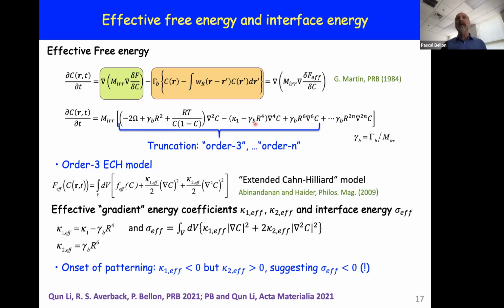But when we look at the second term here, there's something intriguing: when we increase gamma, we may also change the sign of this gradient energy coefficient. And since this is related to the interface energy, that suggests that pattern formation can possibly be envisioned as a mechanism by which irradiation changes the sign of the effective interface energy from positive to negative. But the model is regularized through the introduction of the third term, which is always positive.